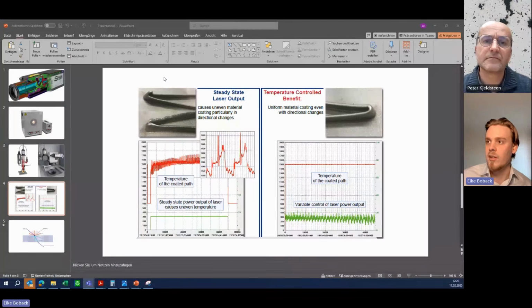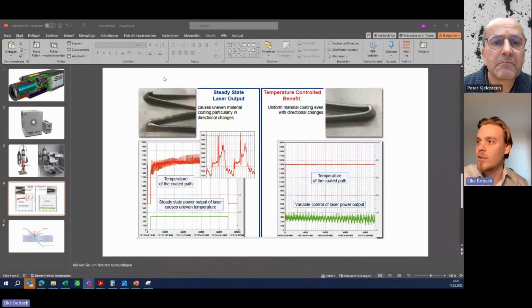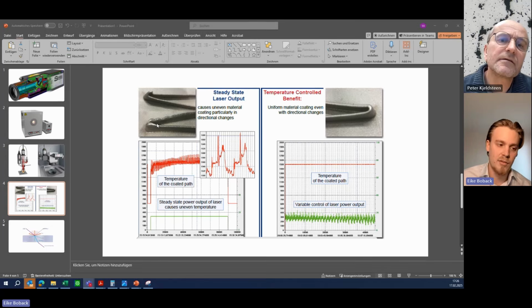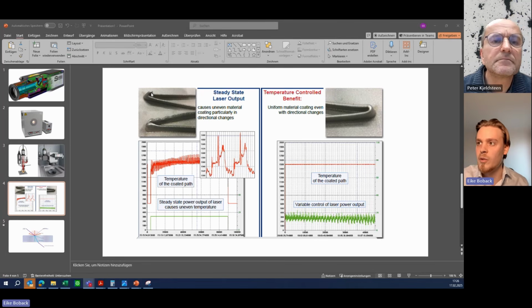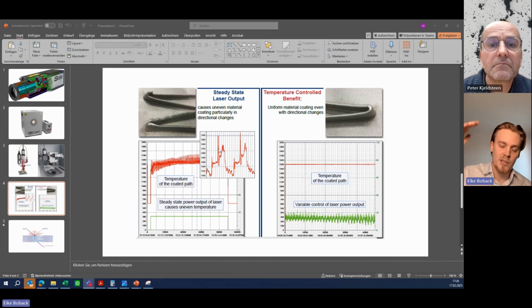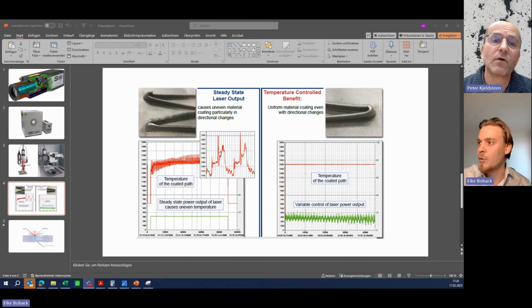And many of the users know some errors coming from non-constant temperatures. So as I mentioned on these curves, you also have this on LPBF. There are many effects on the material, which is not good for perfect printing, for welding, whatever you want. And you see very big differences in the temperature, up to 100 degrees up and down and up. Whoa.